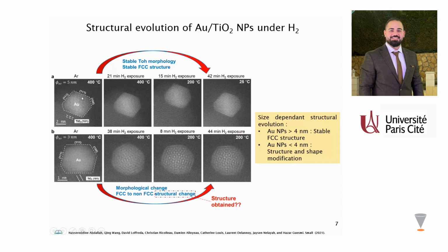As we see, the larger particle keeps its initial FCC structure and truncated octahedral morphology, even to room temperature under hydrogen. However, the smaller particle shows a restructuration of its morphology when exposed to hydrogen at 400 degrees Celsius, leading to complete modification of its crystalline structure and stabilization of an icosahedral-like structure at 200 degrees Celsius.